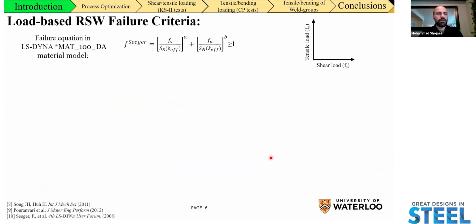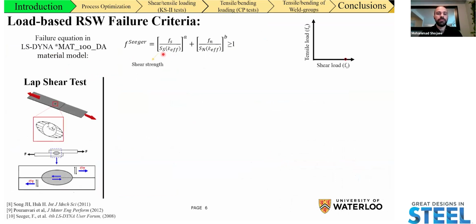Now, the most common failure loci equation, the functional form of the failure loci equation, is proposed by Seeger, that is adopted in LS-DYNA's MAT 100DA material card. Now, as I've shown here, this failure loci uses two terms. The first term deals with shear strength. The shear strength of spot welds is typically characterized by performing lap shear test, which is a standard test. And we can put the shear strength of the weld on a plot like this, where the x-axis is shear load and the y-axis is a tensile load.